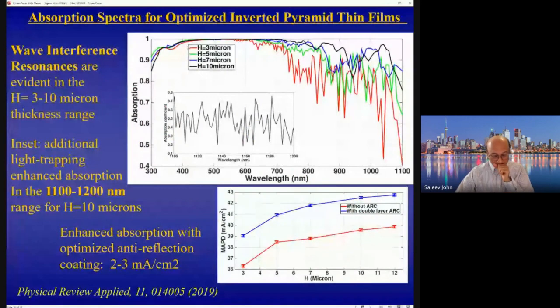Here's a more detailed picture of the absorption, showing the spectrum of absorption as a function of wavelength. And here again, you see structures of different thickness ranging from 3 to 10 microns, starting from the red curve going up to the black curve. As a function of wavelength, you see these oscillations in the absorption. These are the signatures of optical resonances taking place in the structure. And so the absorption is getting pretty high in this region where you're very close to the indirect band gap of silicon itself, due to the very slow light effects.